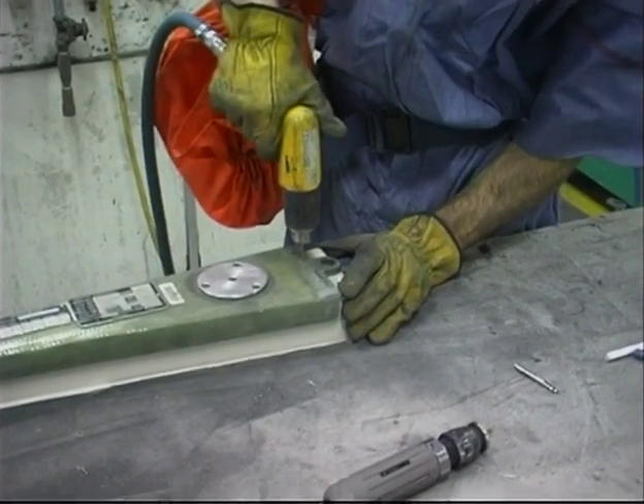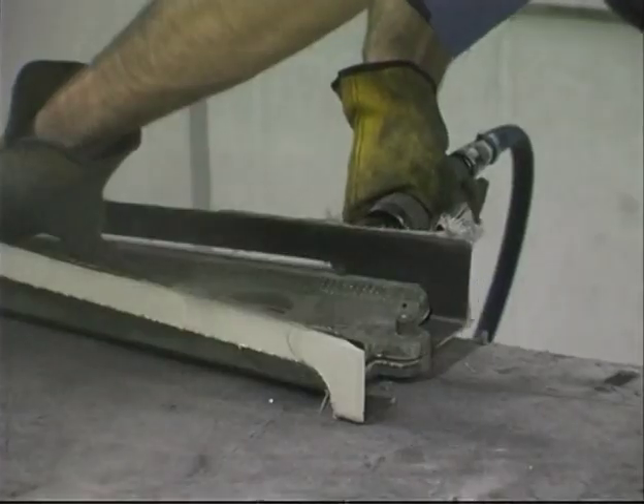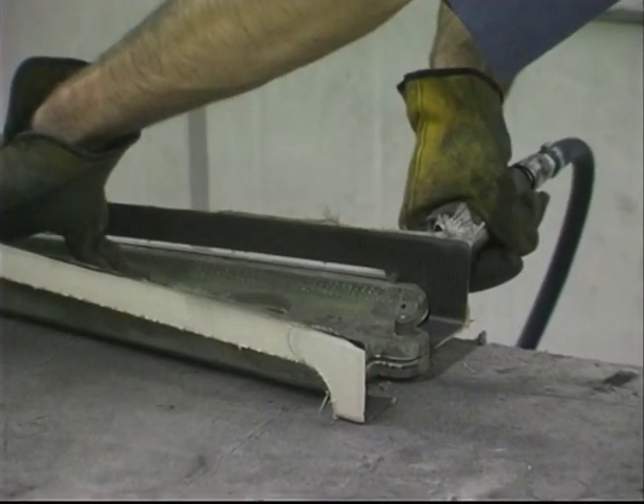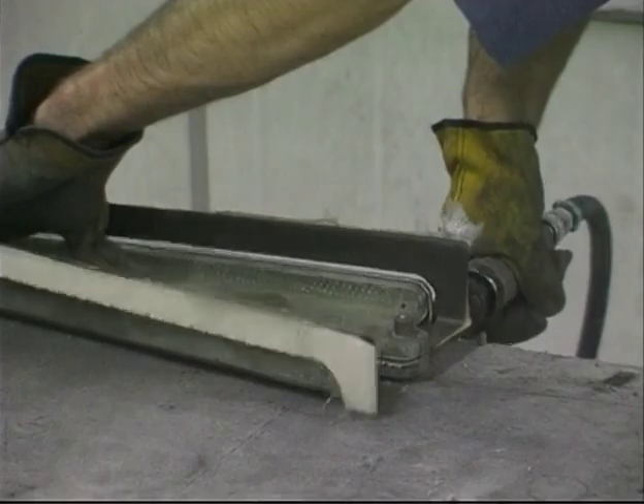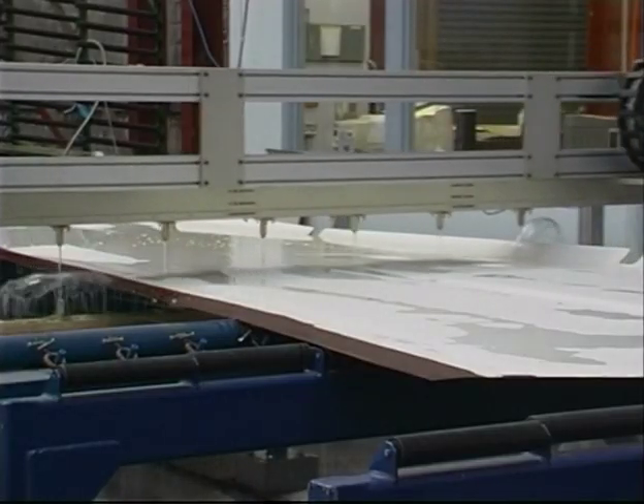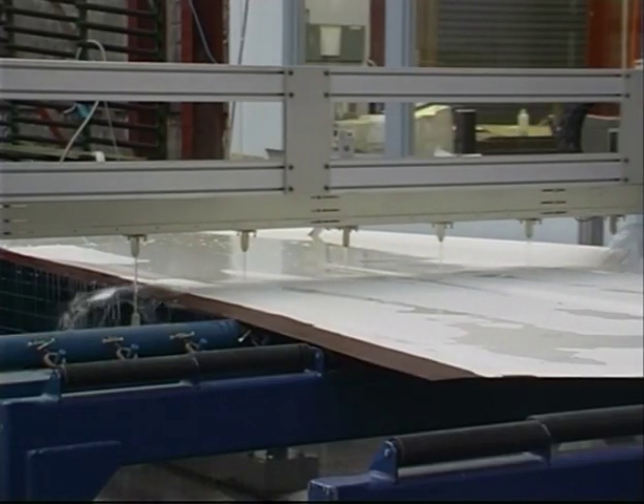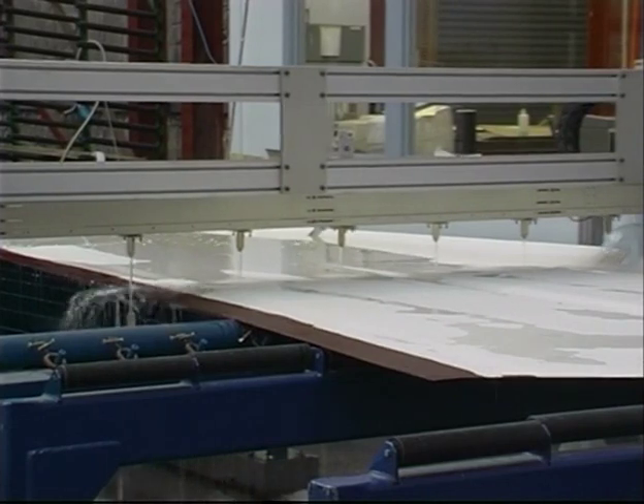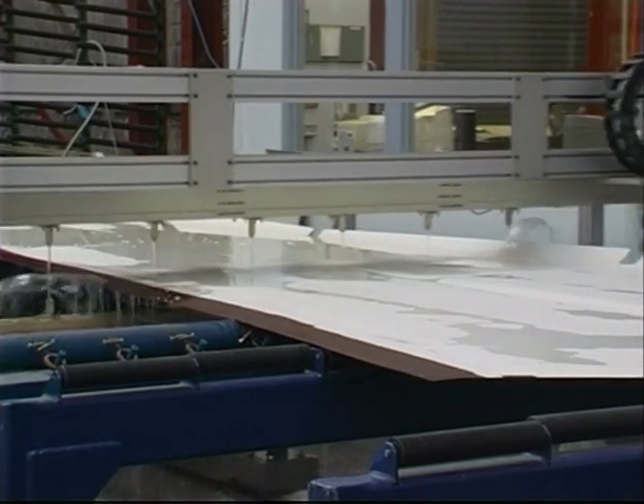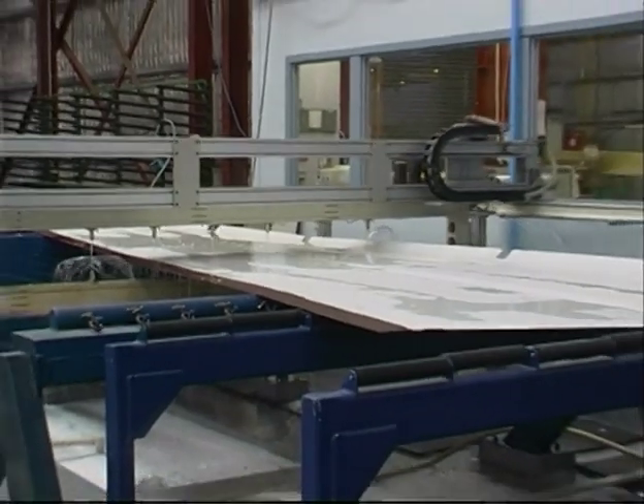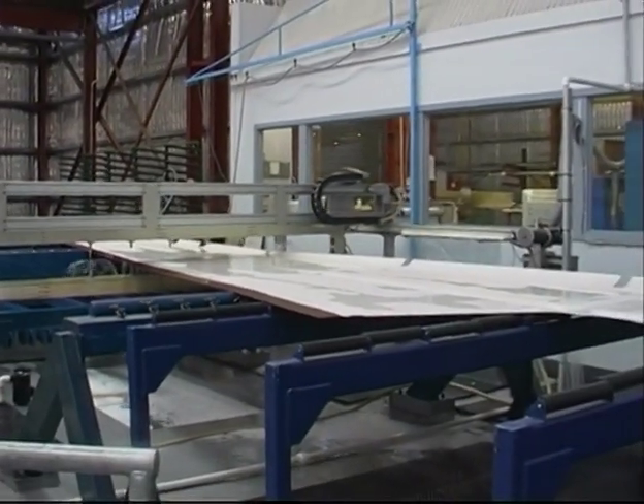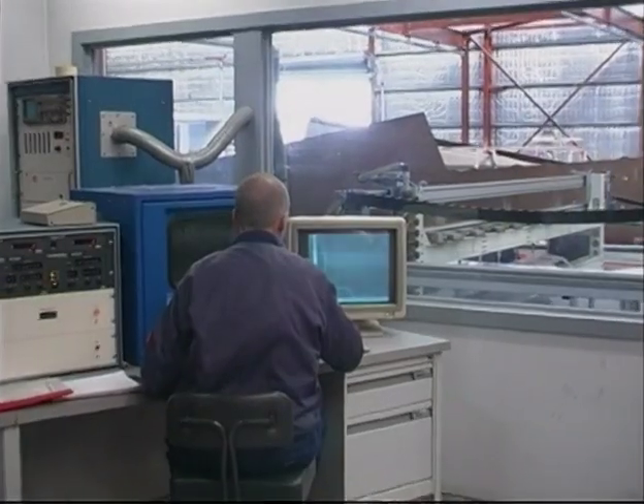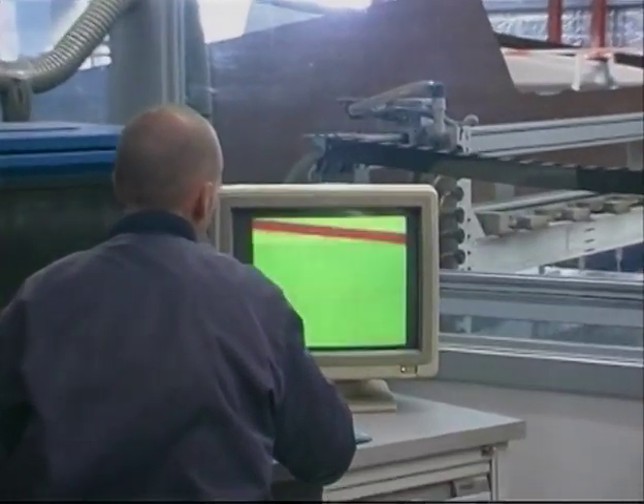With the aid of a jig, the smaller parts are drilled and trimmed to size. The finished parts are non-destructively tested. A large skin by through transmission ultrasonics. The sound waves are transmitted through the top and bottom water jets. If there is a defect in the part, the pulse is partially absorbed. The results are displayed on a screen or they can be printed out.